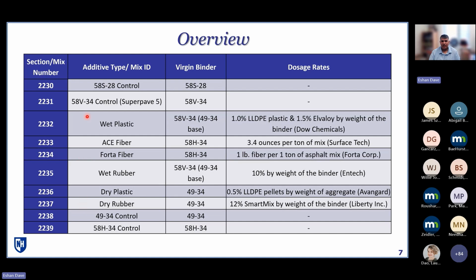And for the additive group mixes, they were also mixes that were designed using the BMD approach by NCAT, by Auburn University, where they had to meet a certain threshold. So more details you can find in the additive group pooled fund website. They actually have all the details on the mix design and how the mixes were finalized and so on. The wet rubber has about 10% by weight of binder as the rubber additive. With dry plastic, it's again the LLDPE pellets that were directly added at 0.5% dosage by weight of aggregate, so quite a bit of that in there. And then dry rubber used the product called Smart Mix by Liberty that is added into the mix as well.